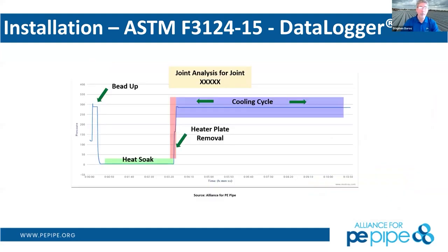So this is what a typical graph from a data logger will look like. This is pressure on the y-axis and time on the x-axis. First of all, in the first few seconds of the fusion process, you're going to bead up. What that means is you're going to bring those pipe ends together that you've already faced and got very clean and uniform and parallel to each other, so they're very symmetric, and you're going to bring them up against the heater plate. The heater plate is going to then start to bead up. You're going to see a melt bead all the way around that pipe.